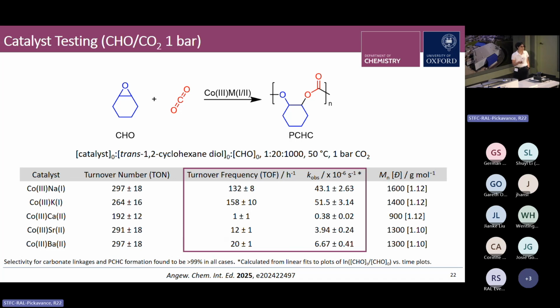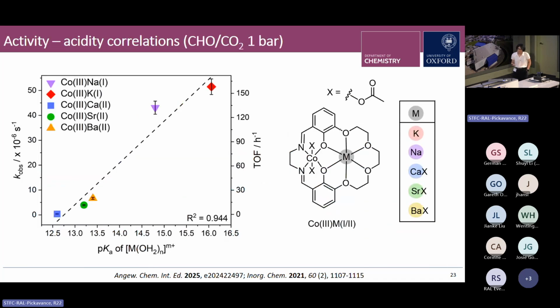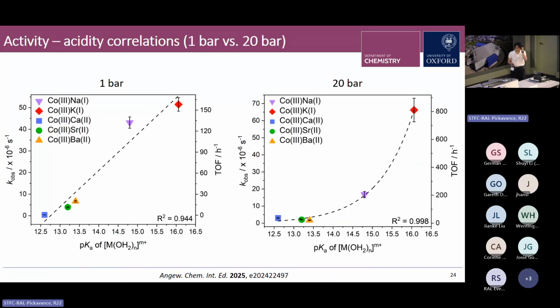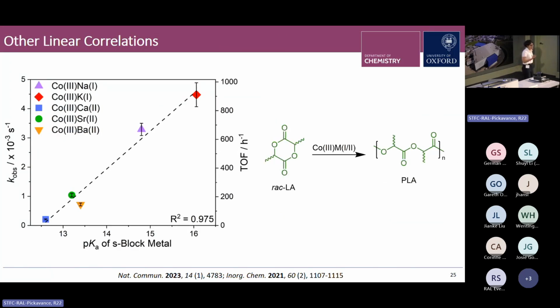So if, as before, we plot these values versus the S-block metal Lewis acidity, we see that the correlation is more linear in nature. So just as a side-by-side comparison, for the same series of catalysts for the same reaction, the copolymerisation of CHO and CO2, at 20 bar CO2 pressure, the activity-acidity correlation is nonlinear or exponential, but at 1 bar CO2 pressure, the correlation is linear. But this is not the first time that we've seen linear activity-acidity correlations. We've also seen it for the same series of catalysts for the ring opening polymerization of lactide.